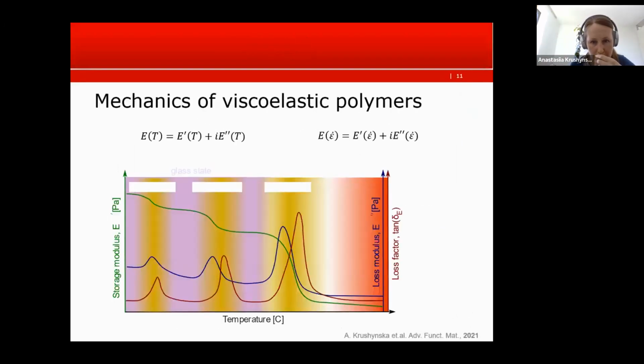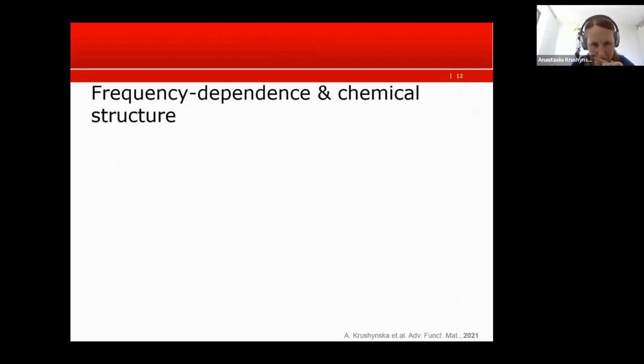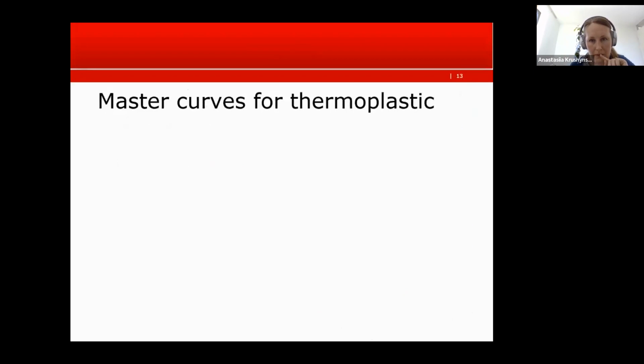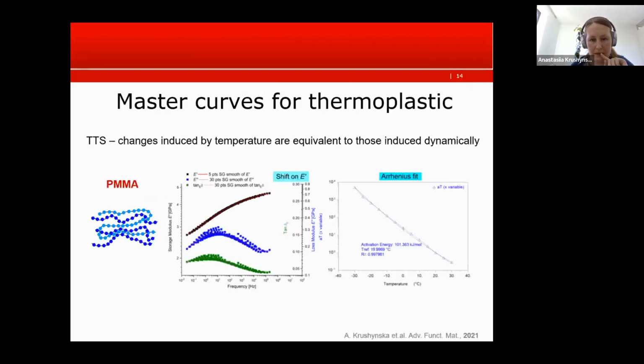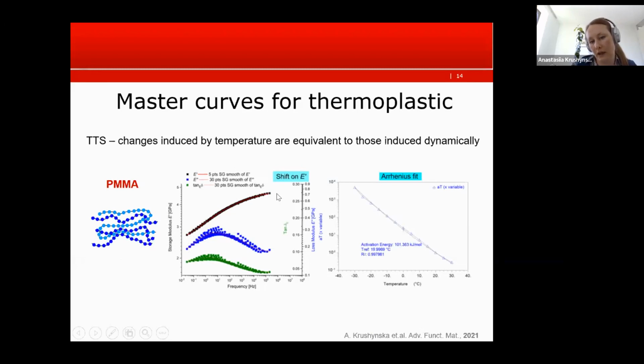In the work there, we measured properties. So let me go quickly to that part. So this is for PMMA material. Here, if I remember correctly, there were also around 15 terms. And we fitted the data in the frequency range which was measured, plus 2 additional terms that represented the behavior in the rubbery zone and in the glassy zone, which were obtained from other experiments. So not a time-temperature superposition, but we had to also match the limits. So this is how it worked.